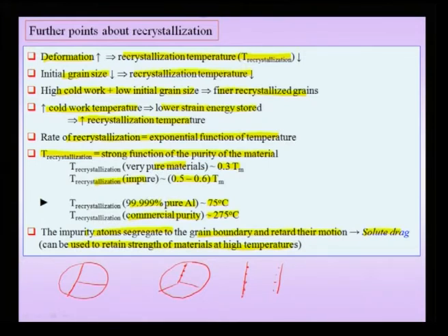Therefore, what would happen is that these elements have to diffuse along with the grain boundary so that they can remain segregated at the grain boundary, and this whole process, that means this coupled process, is less free as compared to just the motion of the grain boundary. So, these pure grain boundaries can move easily, while grain boundaries with segregations cannot move that easily, and therefore these grain boundaries feel what you call a solute drag, and in the process recrystallization is difficult in such materials, and this solute drag can be used to retain the strength of materials at high temperature. That means you do not have recrystallization taking place readily. That means the energy put in as cold work, the stronger material remains strong even at higher temperatures.